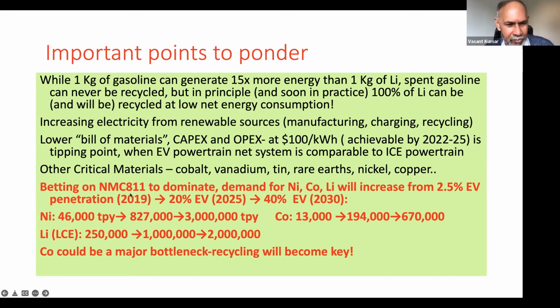If you bet on NMC 811, the low cobalt material, for the future to dominate, and this is the direction in which Europe is going, the demand for nickel, cobalt, and lithium will increase in unbelievable quantities from 2019 to 2030, with 20% electrical vehicle penetration in 2025, assuming one scenario. That's a very rapid growth, from 2.5% now to 40% in 2030. These are massive turnovers in a very short time, but there is a possibility this is going to happen. So nickel, you can imagine, from 46,000 tons, is going to 3 million tons per year.